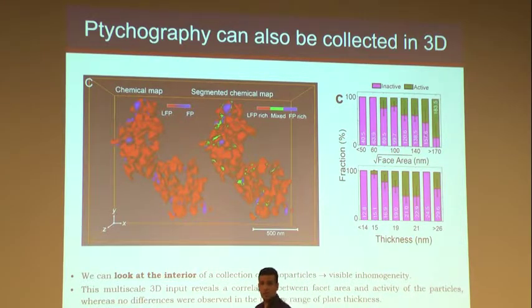The first thing we did is use these measurements to identify where the particles were and what the dimensions were. And so the plot on the right, what that's showing is the level of reaction for each particle. You can see that they all are at different states. So by the way, these are the same objects. It's just a different scale to depict the chemistry. Okay? So it's the same thing.